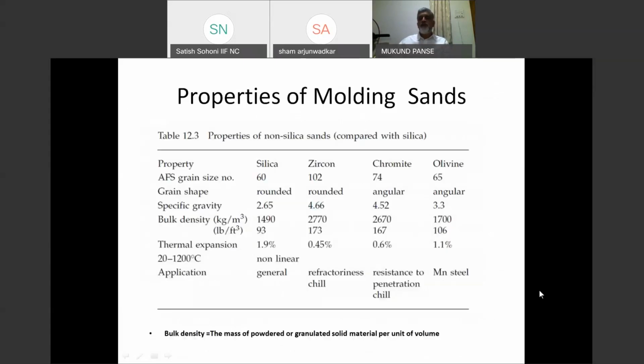This is a comparison of molding sands. AFS grain size is normally what you get. Silica you can get in whatever grain size distribution AFS number you want. Zircon you get much finer. Chromite and olivine also, but with chromite and olivine it is difficult to get the 3 or 4 sieve distribution which you normally seek to have proper compaction of the sand grains.